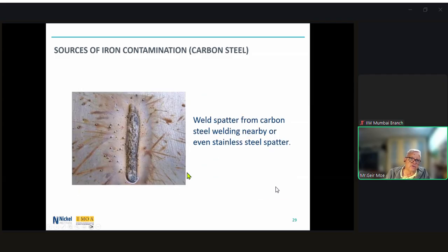But there are other sources of iron contamination. In addition to, say, just simple grinding on carbon steel nearby, it could be weld spatter from carbon steel welding nearby, or it could even be stainless steel weld spatter, because stainless steel weld spatter is highly oxidized, it has less corrosion resistance, it lands on the surface, and it could even rust and cause rust spots.